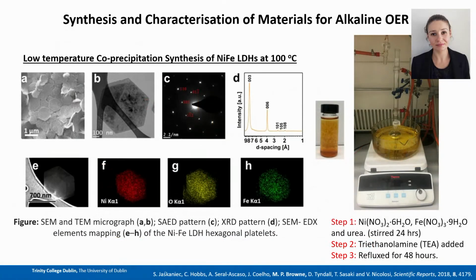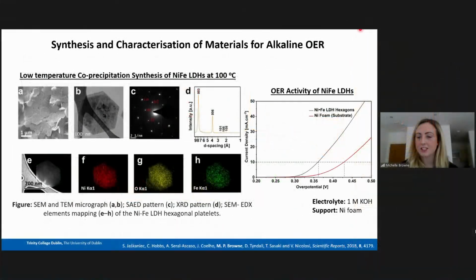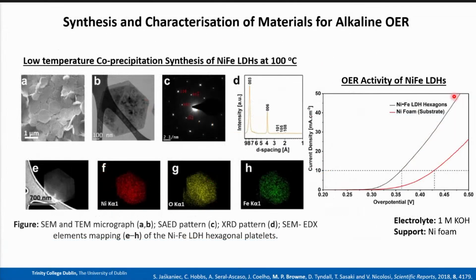So further on, we wanted to look at the OER activity of these materials, because there was no point in doing more studies if our material wasn't OER active. First of all, the material was sprayed onto nickel foam, which is a well-known support for OER in alkaline media. If we then look at the LSV curves here for the OER activity, the red curve is just the bare nickel foam. And then once the nickel-iron LDHs are deposited, we can see that we get an increase in OER activity. So everyone was very happy.